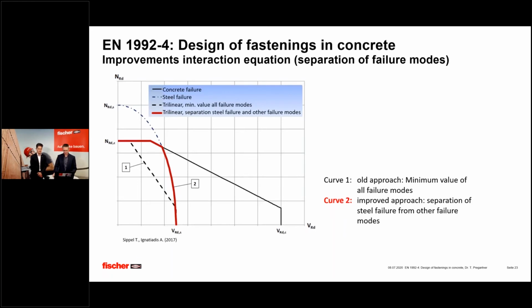Now, what does that mean? I'll try to show that in one graph where you show the design resistance in tension on the y-axis and the design resistance in shear on the x-axis. And you see already that in tension, concrete failure gives the lower value compared to steel failure, whereas in shear, steel failure is decisive. So the old interaction equation required that you do this line 1 if you did it with a linear interaction, which is relatively conservative. If you work now according to Eurocode 2 part 4, then you do first the interaction equation for the steel failure, which gives you this dotted dashed line, and then you have the additional interaction proof with the bold line, with a black bold line for the concrete related failure mode.